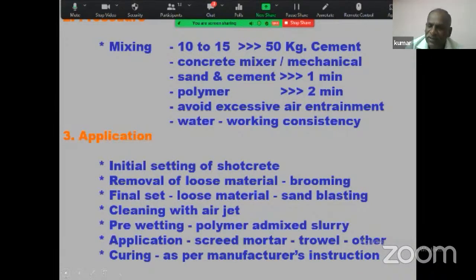Then make a small sandblasting sweep, that is called sweep sandblasting, and cleaning is to be done with the air jet and pre-wetting with the polymer admixed slurry. So the polymer we have used in the polymer overlay, acrylic emulsion, the same thing you can use for pre-wetting. After that, you can apply the polymer based mortar. We can apply by screed, mortar type or trowel or any other means. You can apply on the surface of the shotcrete.